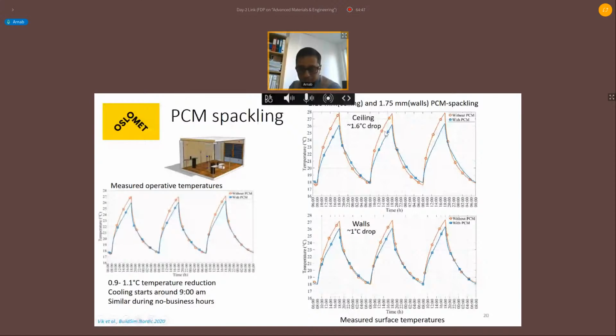So what we did after that, we also measured the thermal conductivity of this material and tried to see whether what the vendor and other groups measured is correct or not. So we did a hot box experiment to measure the thermal conductivity. But essentially, we did this parametric analysis with numerical calculations.